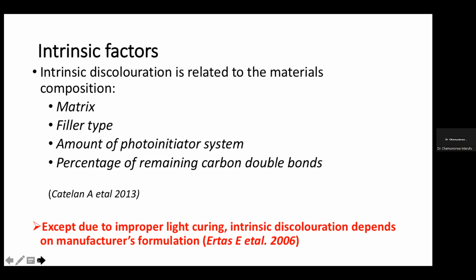We also know that composites with larger particle size of the fillers are more difficult to polish, so they'll tend to absorb and stay more and discolor more. Also, the amount of photo initiator system, this would apply both to light cured system and also self-cured system. The light cured system, which are the ones we commonly use in our clinics, the most common photo initiator is camphorquinone, and unconverted camphorquinone tends to cause a yellowish discoloration in the restoration, and also the percentage of carbon double bonds. So as I said, the intrinsic factors are related to the material's composition. And so except due to improper light curing, intrinsic discoloration depends on the manufacturer's formulation.